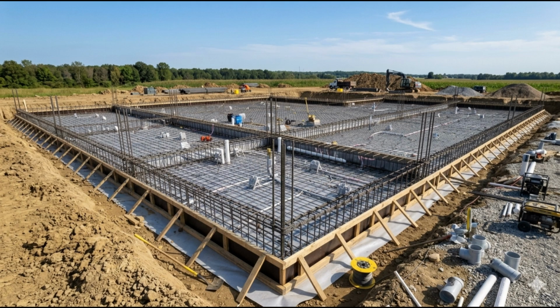Laitance refers to a weak layer that forms at the surface of fresh concrete due to the upward migration of water, cement, and fine particles during compaction and early curing. It is softer than the underlying concrete and, in floor construction, is typically removed by the power floating and troweling process, or by grinding if it proves resistant. Excessive laitance can indicate over-vibration or a mix with too high a water content.